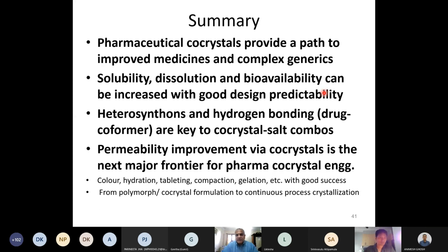Therefore, we need crystal structures, at least for those co-crystal or salt combinations where single crystals are available. And now, of course, electron diffraction allows us to get single crystals of a very, very large number of solids which were not possible in the past. This has also come out in several journals, like compared to paracetamol, orthocetamol does not give single crystals. So that has been determined by electron diffraction. So pharmaceuticals which were not accessible in single crystal structure state earlier are now very easily accessible thanks to multiple techniques, including electron diffraction.